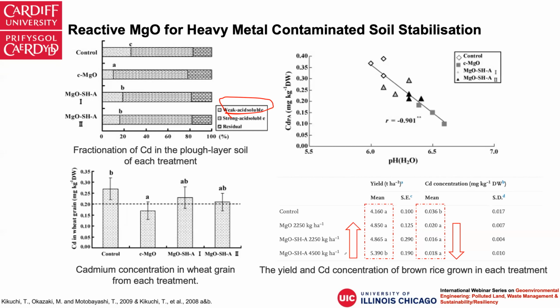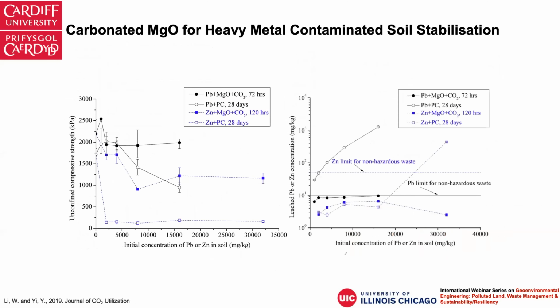So that is a good example of using magnesia just as a soil amendment instead of solidifying the soils. And then go to the cementitious materials again. I mean, we can see that if we are using the carbonation technology, the enforced carbonation, using high concentrations of carbon dioxide to cure the magnesia-treated soils or contaminated soils, we see a significant strength increment after carbonation of only a few hours.